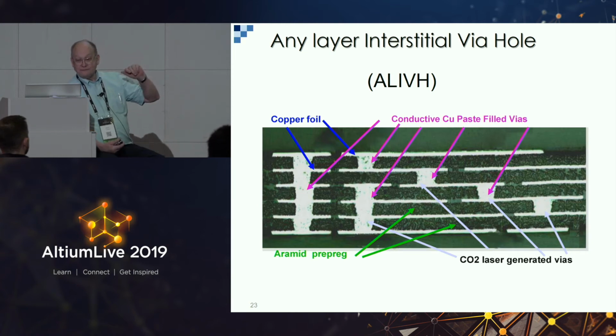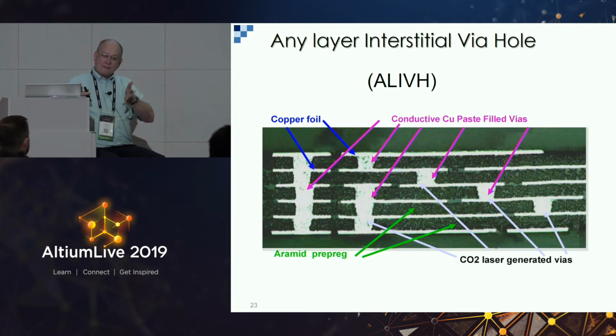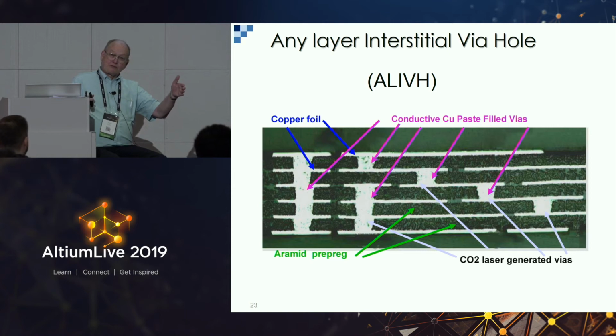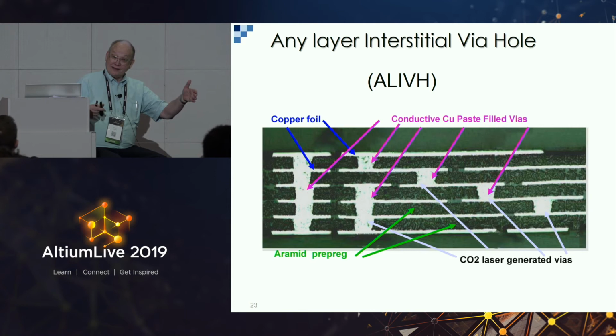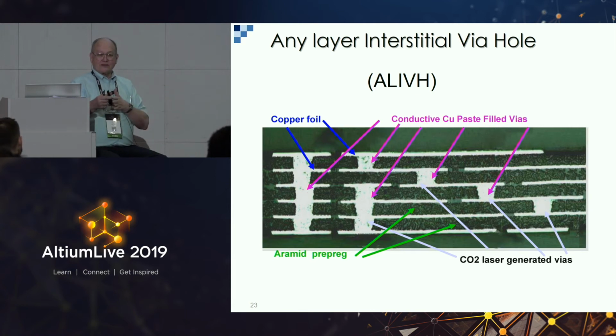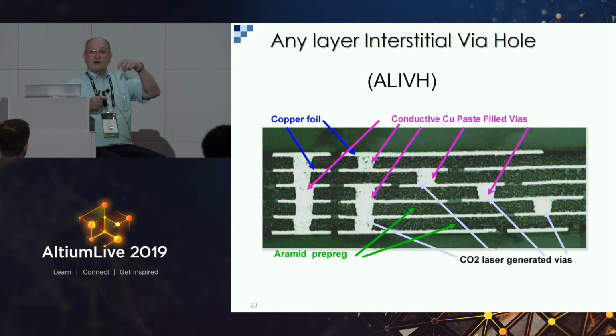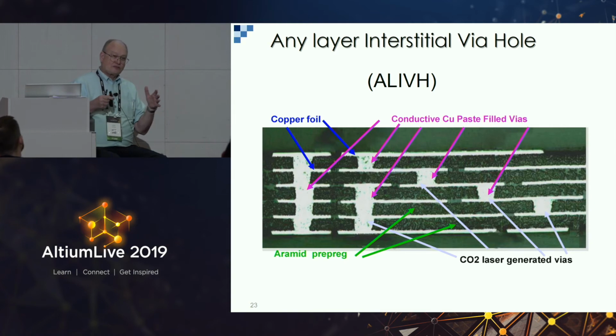Okay. So you take Kevlar that you make bulletproof vests, and Kevlar is filaments. You chop the filaments up, and you put them into a paper making machine, and you draw this out as a paper, but it's a thermoplastic paper made of Kevlar. Okay? The nice thing about this, it has the same coefficient of thermal expansion as silicon. The only thing you've got to worry about is that it's somewhat bulletproof because it's made out of Kevlar. So it's really, really tough to mechanically drill, but it laser drills beautifully. So you don't want to mechanically drill it because after a couple hundred hits you have to change the drill bit because you're going through Kevlar. But it's a Kevlar paper. The beauty is it's extremely smooth, and the coefficient of expansion is just fantastic.